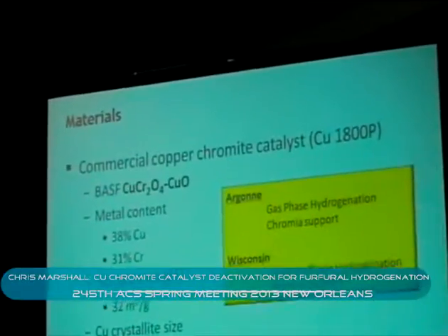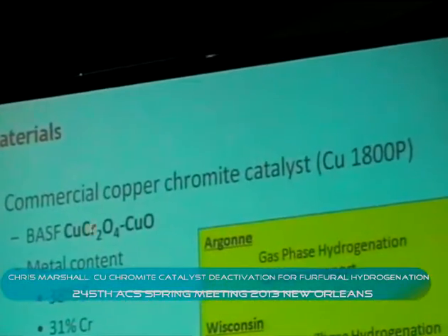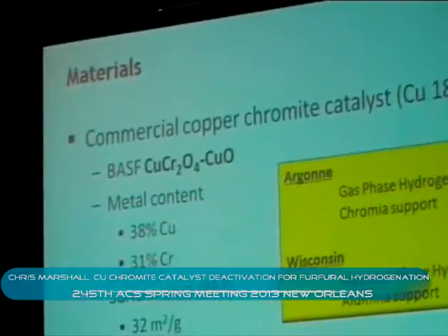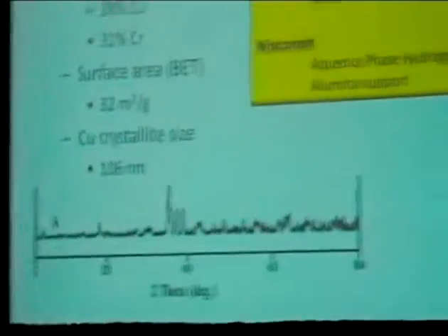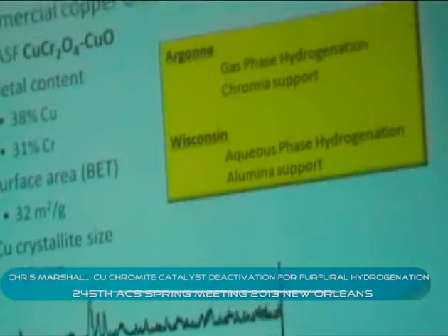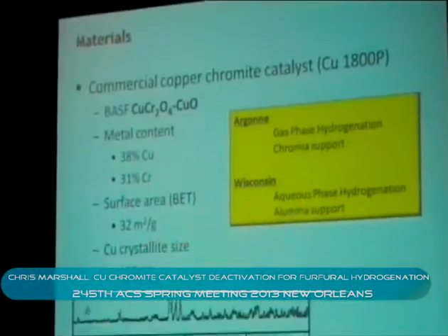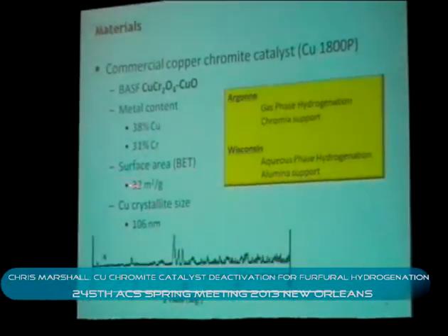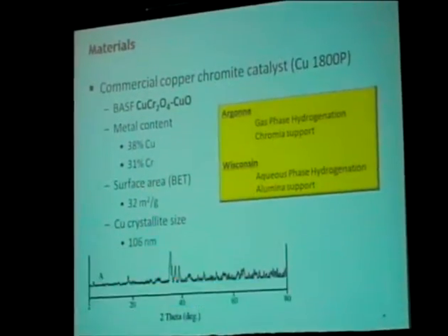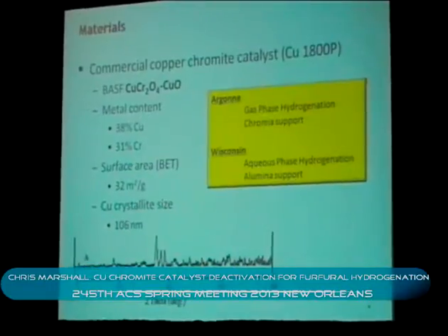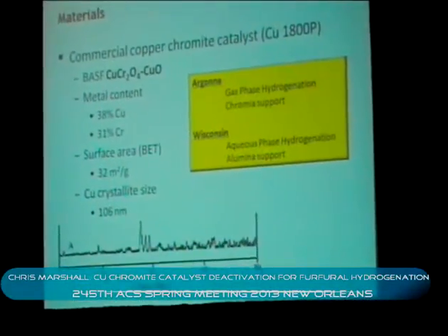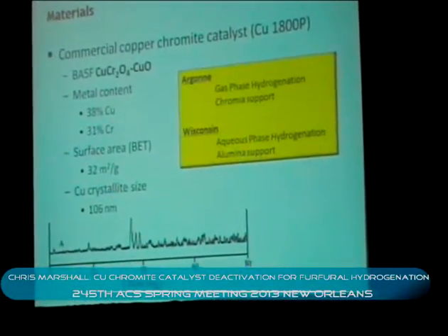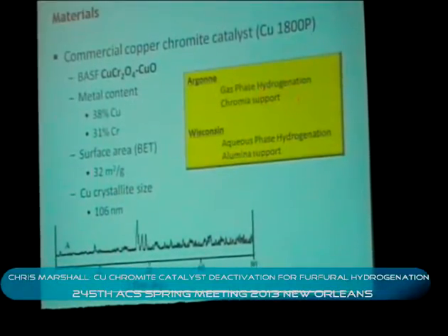The catalyst that we're going to be talking about this morning is a commercial BASF catalyst. It's a mixture of copper oxide on chromia with a metal content you see here, essentially. There's no support other than the chromium oxide for this catalyst. It's been commercialized for a number of years, fairly high surface area for this type of material, but very large copper crystallites.